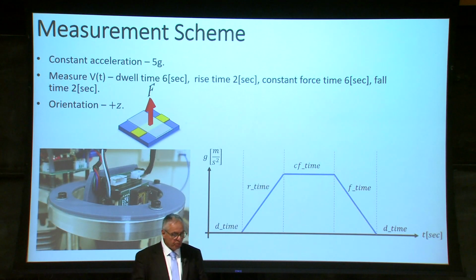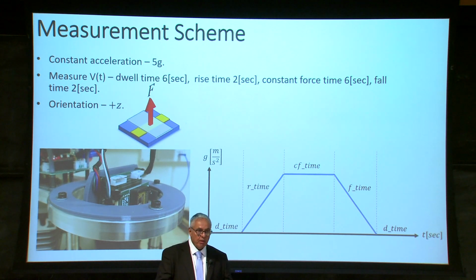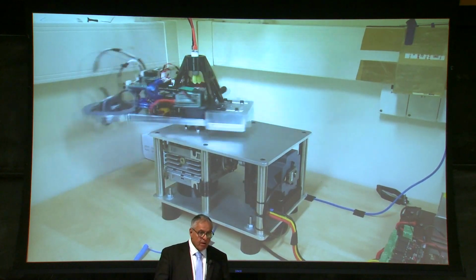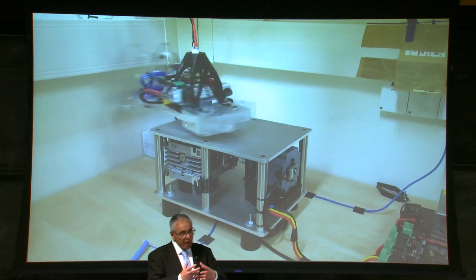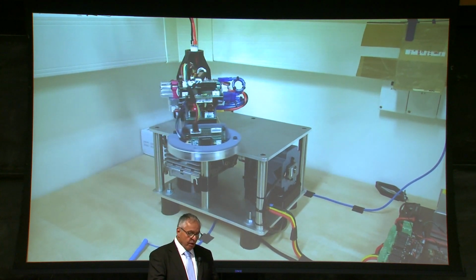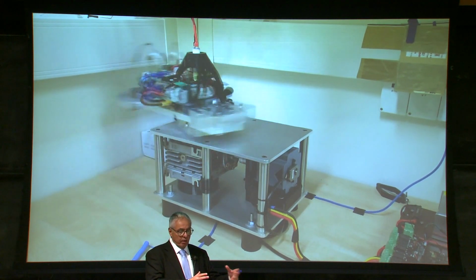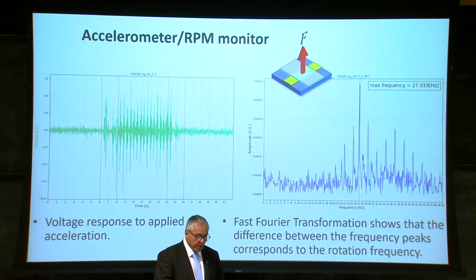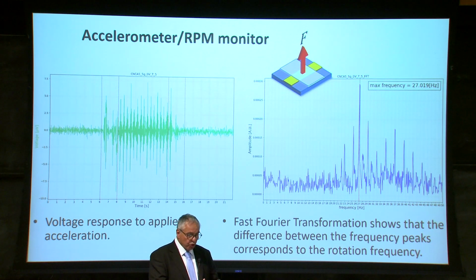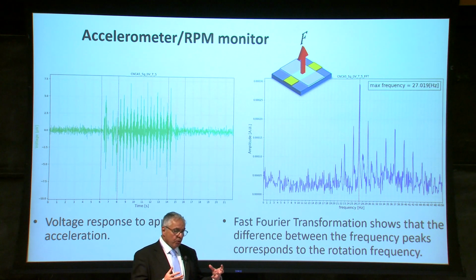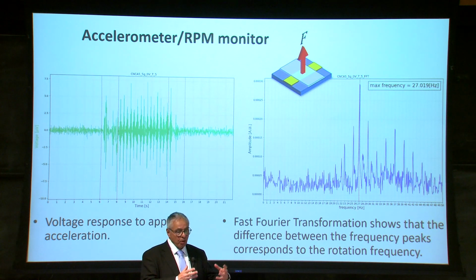Omer also developed, because his background is in mechanical engineering, so he likes to build things, a really nice device that enabled him, on one hand, to measure the force under constant G. And you can see here some of the data. You can see a voltage response to the applied acceleration. But more interestingly, when he did a fast Fourier transformation on that data, he was able to show that the difference between the frequency peaks corresponds to the rotation frequency. So in a way, it is not just an accelerometer, but also an RPM monitor.